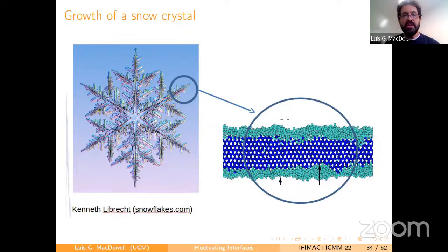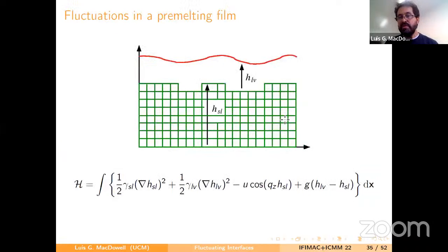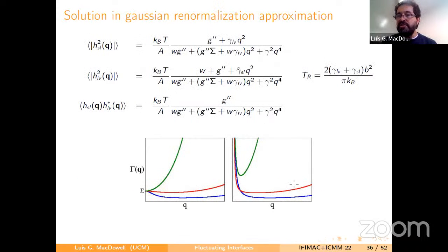bulk vapor phase. Okay. So the way to study this is not with the simple sine-Gordon Hamiltonian that I showed before, but instead we need to write a model for the free energy that actually is the sum of these fluctuations, the energy cost of making these fluctuations, and the energy cost of making these other fluctuations. Okay, and the two film thickness positions, film height positions, actually are coupled via this interface potential, which dictates the preferred thickness of this pre-melting film.